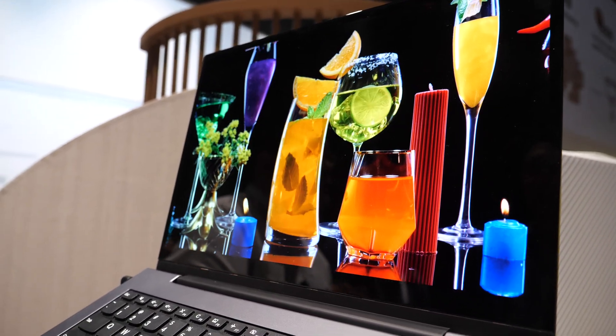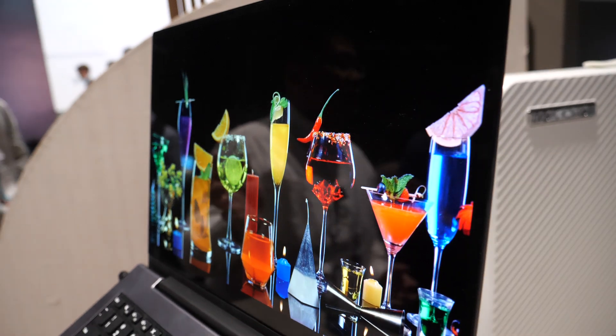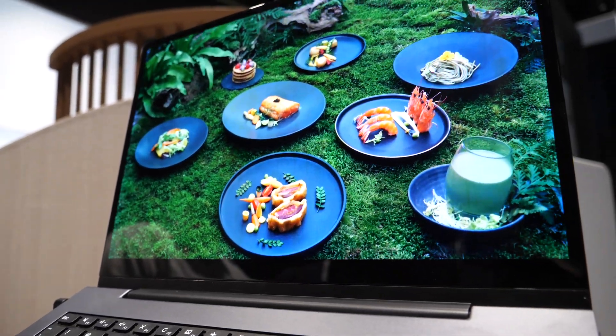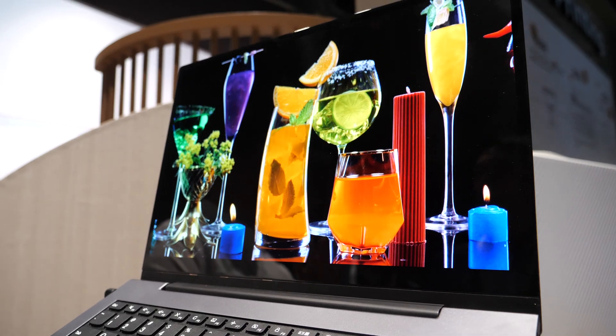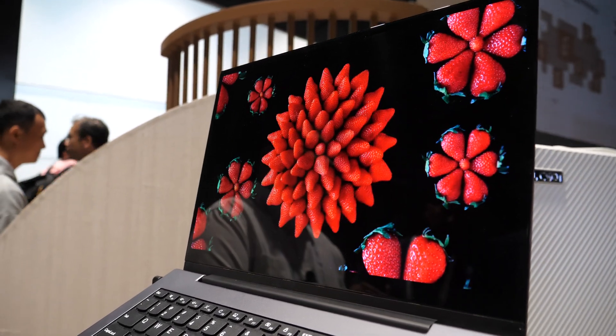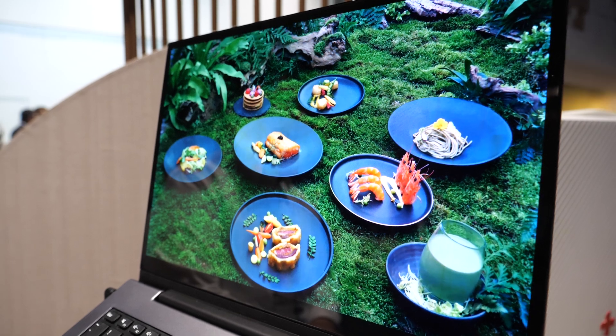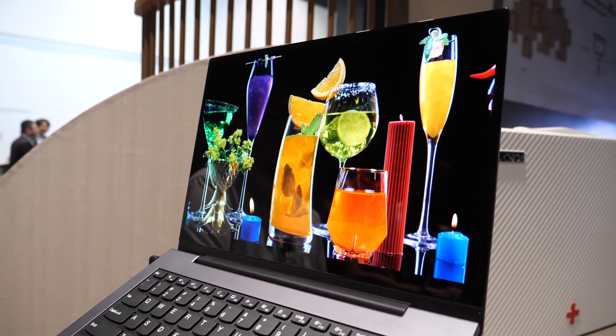What about the lifetime? The red and green are not a problem - they already have a similar lifetime as OLED. But for the blue, it's still trouble. Can you quantify? The blue T95 at 1,800 nits is around 100 hours. For OLED, it's about 400 to 500 hours. So it's specified at 100 hours, but in reality it's much longer.